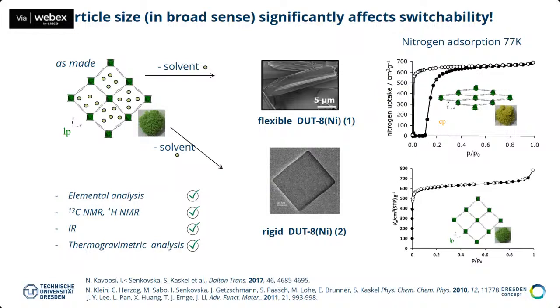But when you desolvate it, you end up in a metastable open pore form. And here you see this open pore form basically because this material takes up the gas immediately from the beginning. And also there's no hysteresis at all, so that's the characteristic. And we find this as a general phenomenon. Often, when we make nanoparticles, the material becomes rigid, while if we have big particles, the material is flexible. There are also a few rare cases where it's the other way around, that the material becomes flexible when it's small particles, but in many cases it's the other way around. This depends on the energetics of the material.